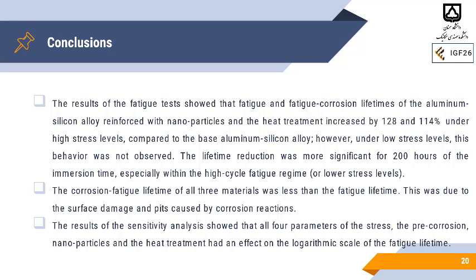The lifetime reduction was more significant for 200 hours of immersion time in the corrosive fluid. So this behavior was more significant with the high fatigue lifetime or lower stress level. The corrosion fatigue lifetime of all three materials was less than the fatigue lifetime. That was due to the surface damage and pits caused by the corrosion reaction. And the result of the sensitivity analysis showed that all four parameters of stress, pre-corrosion, nanoparticle, and heat treatment had an effective influence on the logarithmic scale of the fatigue lifetime.